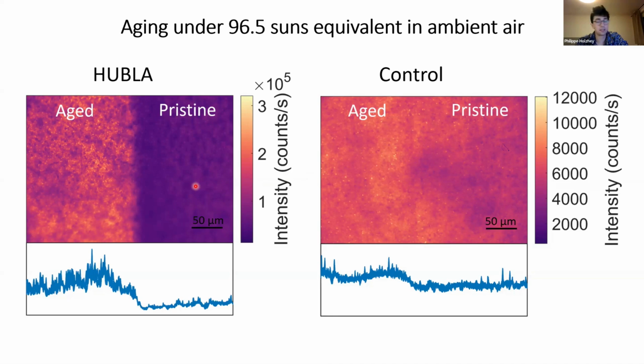And then you can nicely see the change in PL, which was induced through this exposure to light. And you can nicely see here, this is a cross section essentially through the middle, how the PL signal is a lot higher for the exposed area.